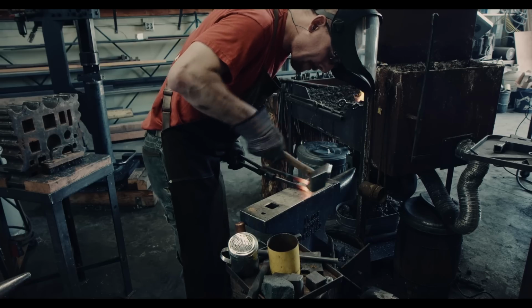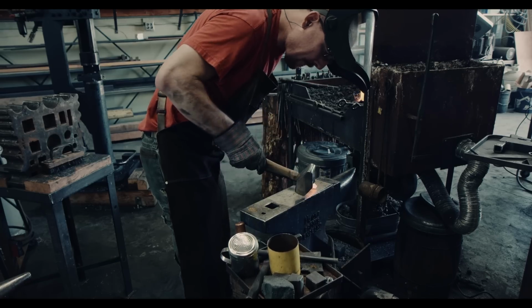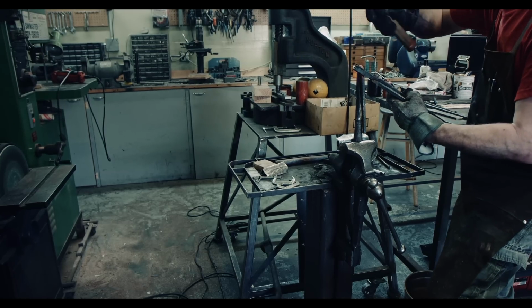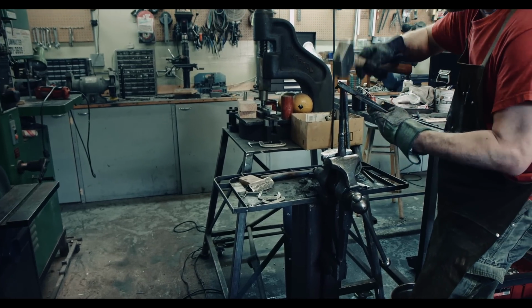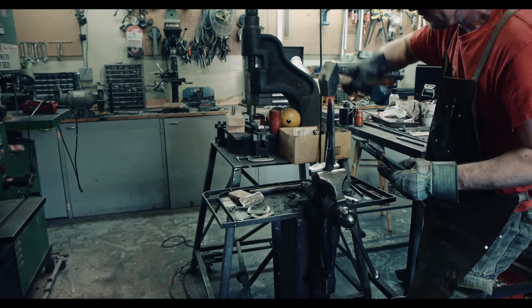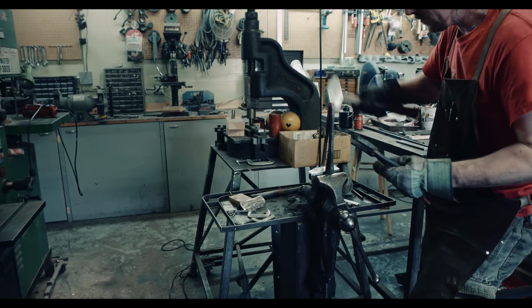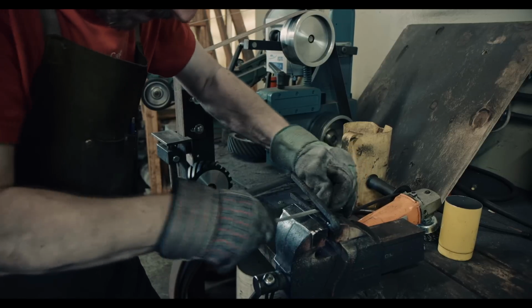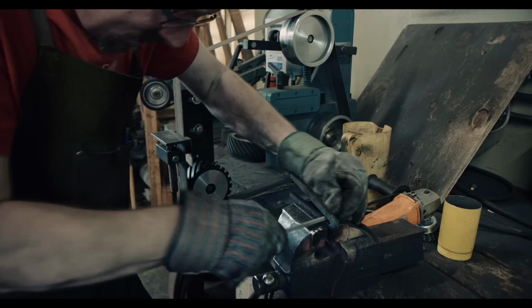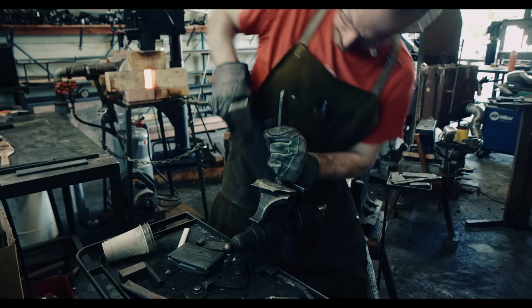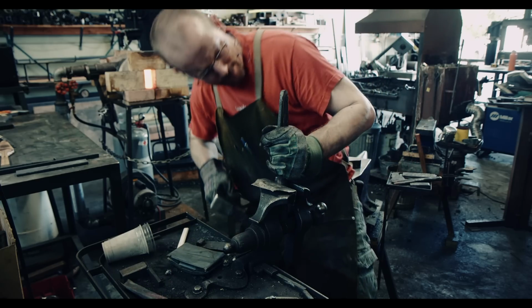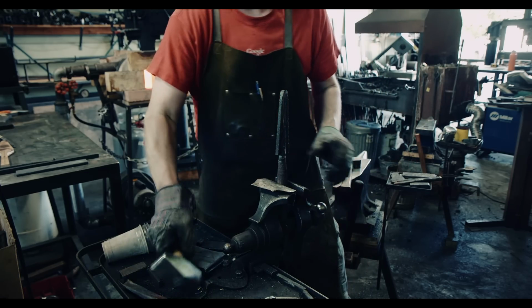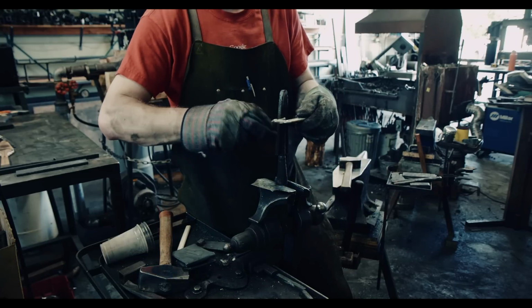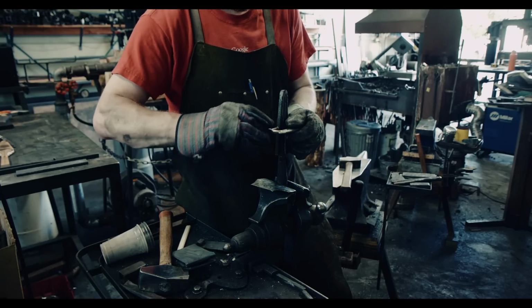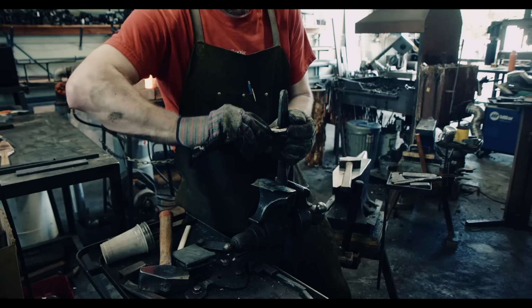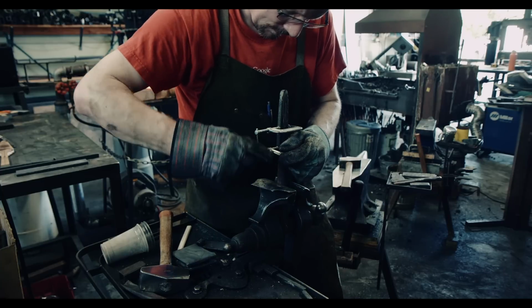So let's use the coal forge after all and do some corrections with the hammer. To successfully weld the bar I just bent to the core of the spear, I need a very precise fit without any gaps. As I had heated the bar for bending, some of the resulting scale needs to be removed again, and a small file is appropriate for the job. Everything seems to be fitting now, and I really hope that all of this is going to come together. A failure here would ruin all the work done so far.